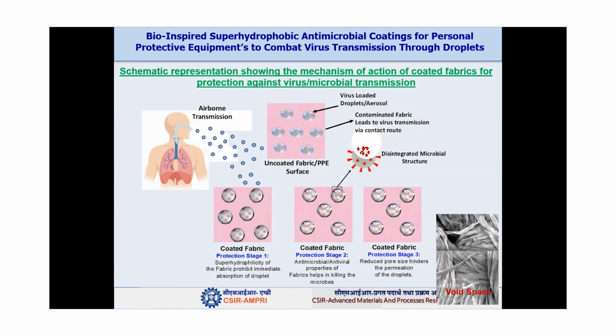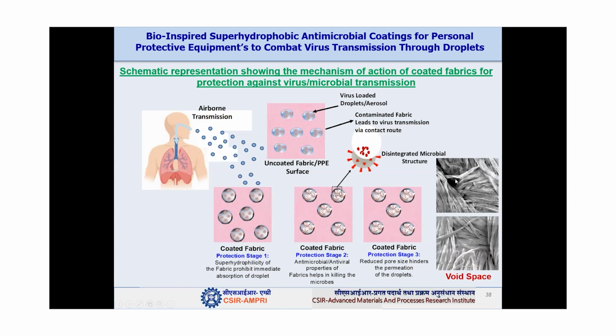the porosity of the fabric due to this coating. You can see here this is the void available on the fabric, but when we coated the fabric with the coating, you can see the void space is completely covered. So definitely the permeation of the virus or the bacteria inside the fabric will be reduced due to the reduction in void space.